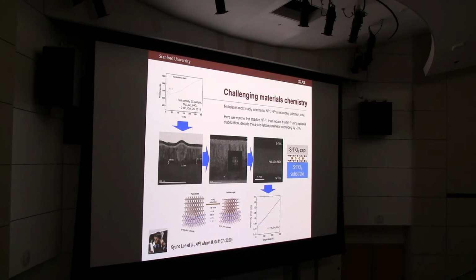We're trying to do this in thin films, to use epitaxy to stabilize our structure, but all the while as we go from this phase to this phase, the lattice constant expands by about 3%. So it's a really kind of a catch-22 kind of problem that's been quite fun, but certainly challenging to work on. And the first hints of anything interesting